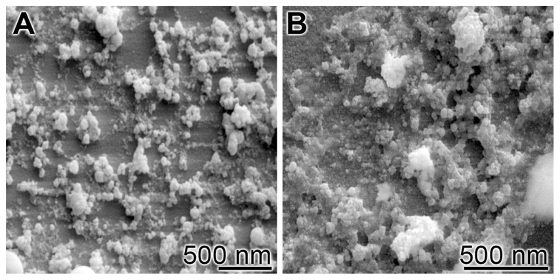When implanted, bioglass 45S5 reacts with the surrounding physiological fluid, causing the formation of a hydroxyl carbonated apatite (HCA) layer at the material surface. The HCA layer has a similar composition to hydroxyapatite, the mineral phase of bone, a quality which allows for strong interaction and integration with bone. The process by which this reaction occurs can be separated into 12 steps. The first five steps are related to the bioglass response to the environment within the body and occur rapidly at the material surface over several hours. Reaction steps 6–10 detail the reaction of the body to the integration of the biomaterial and the process of integration with bone, occurring over the scale of several weeks or months.